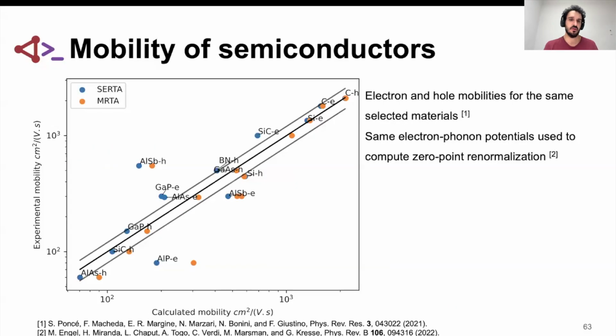Here's another example, computed with VASP, just obtaining mobility of different semiconductors, either electron or hole mobility. This is the same selection of materials as this reference paper, and the electron-phonon potentials are the same ones used to compute the zero-point renormalization, using relaxed lattice parameters.